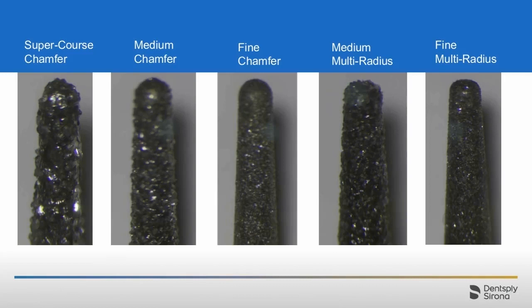This is showing some close-up images of some different burrs. You can see when we look at super coarse chamfers and blow it up under a microscope, that burr is quite abrasive and quite aggressive. So a lot of times I may start with a super coarse chamfer, but I want to make sure I move into a medium or a fine to smooth that area out. The smoother the margin is, the better your marginal gap is going to be, or the smaller it's going to be. So the question is, can I go from super coarse to fine, or do I have to go from super coarse to medium to fine?